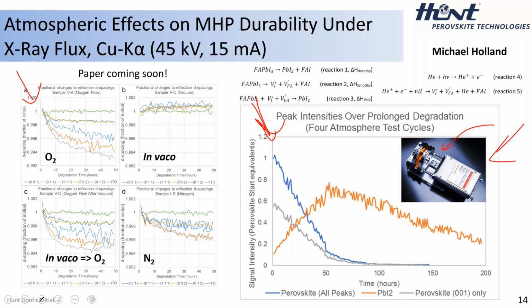And you can see that all the perovskite peaks, this is the summation of the signal intensities, or just the 001 peak, which is the preferred orientation of the material, decrease with time to about 50 hours while the signal for lead iodide increases. But then the signal for lead iodide also decreases. So where in the heck is the lead iodide going, right? That's a big question. But certainly under this elevated temperature, under the bombardment of X-rays in an oxygen atmosphere, we have an issue.